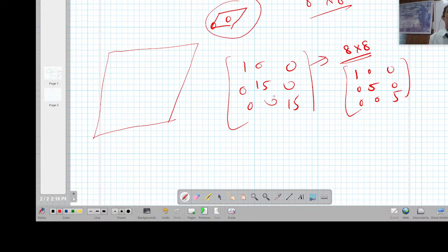This is a very important point, because people are interested in using doping, adsorption and absorption like that. For that you have to keep these things in mind. Otherwise the computational cost will go very high. Sometimes people will also use a 30 by 30 by 30 block. But in general, if you are repeating it, say, 4 times, then you can divide the K mesh by 4. But if you take a little bit larger K mesh, it will do better integration and give you a better band structure.